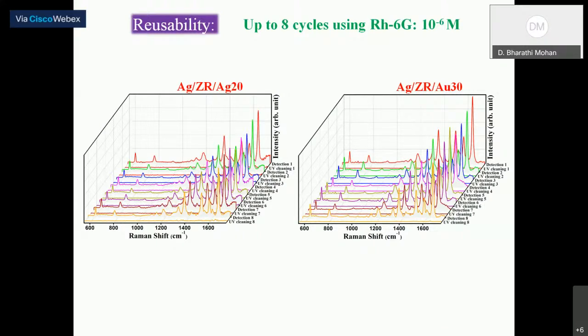So we have done the reusability study, and we have tested this same substrate, and we have detected the rhodamine 6G up to 8 cycles. So you can see this is the first detection, and after photocatalytic reaction, the rhodamine 6G is completely removed, and then again the rhodamine 6G was drop casted, and then again we detected with the same intensity, and this has been repeated continuously for 8 cycles, and we found that even after the 8th cycle, you can reuse the same substrate to detect the rhodamine 6G probe molecule. And this has been verified again with the gold-based hybrid nanostructure.